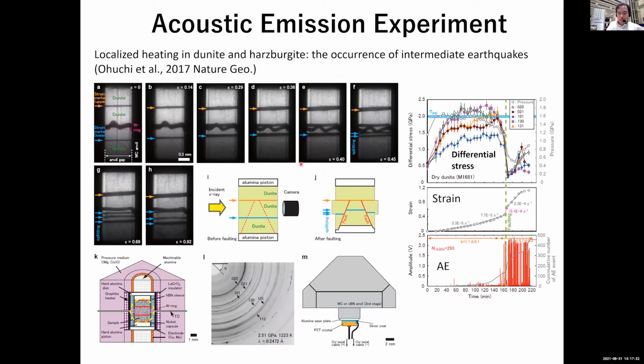This is an example of an acoustic emission experiment using the deformation DIA apparatus. In this experiment, the differential stress of the sample is increased by ram pressure, and microscopic sample strain was detected by radiography. The formation of the main fault was detected from acoustic emission measurement. The change in the frequency of acoustic emission was also measured continuously using this system.